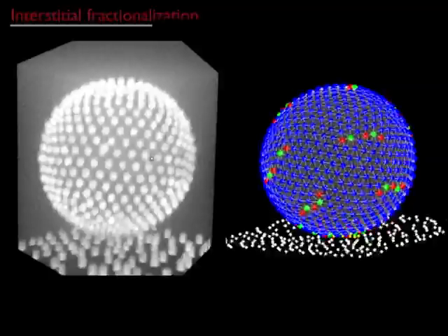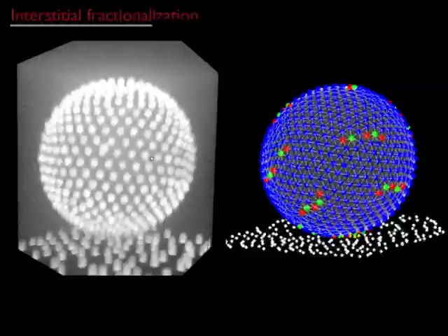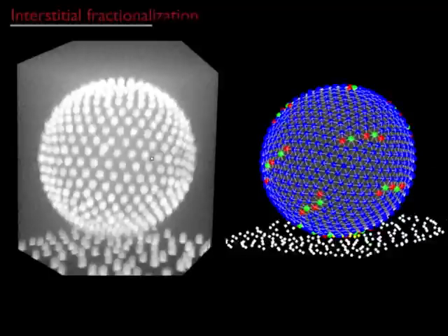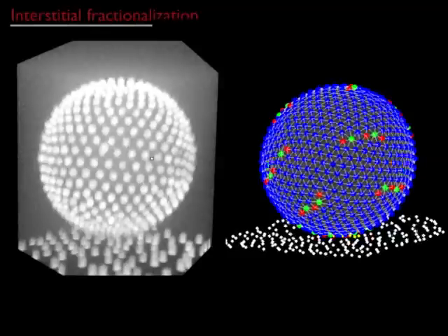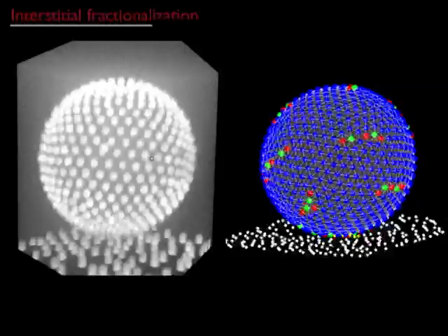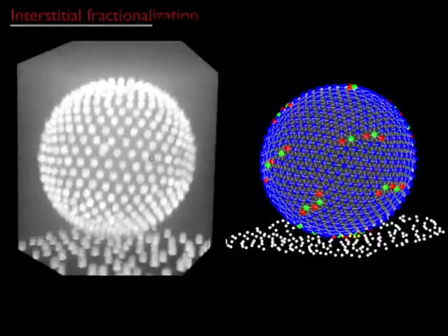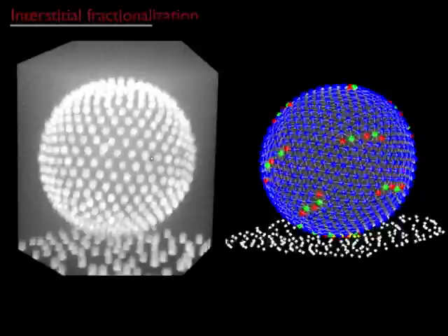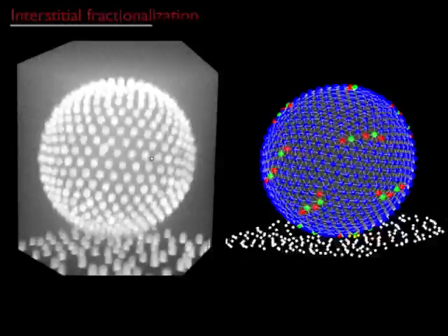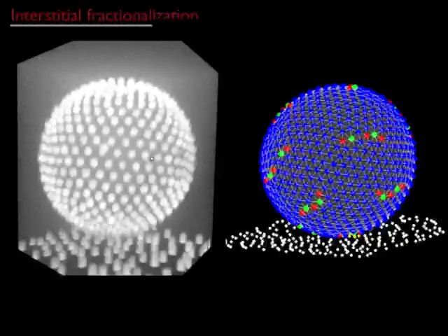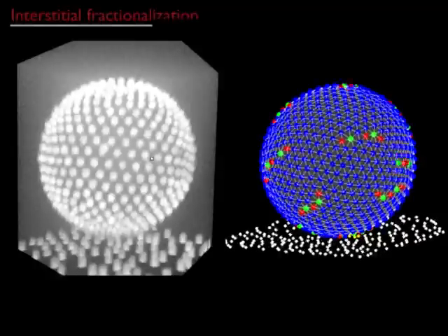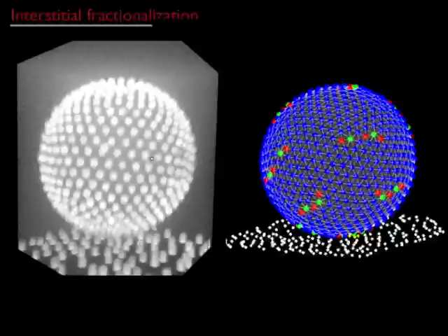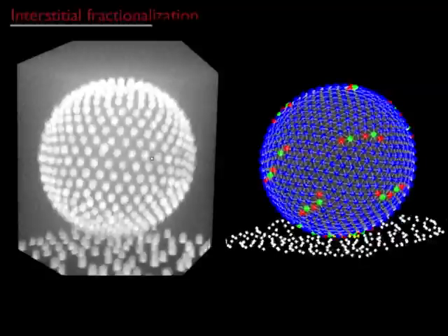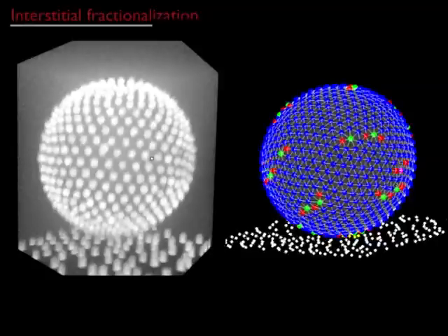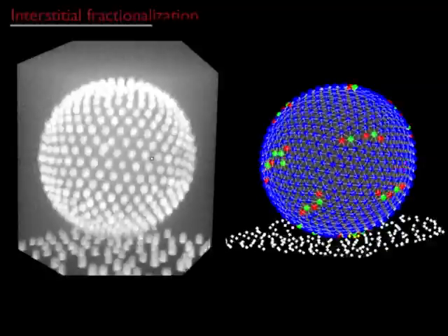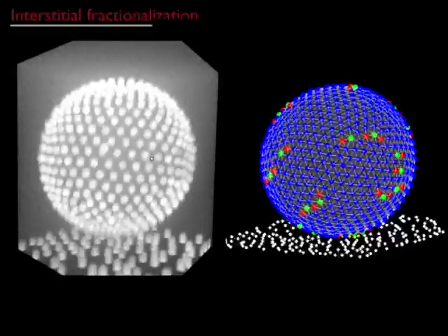Where's the particle? What happened to the particle that I added? Well, of course, the particle's there. It's one of these guys. But if I look at what happened to the extra density that I added to the system, half of the density went that way, and half of the density went that way. And it's perfectly right. This is the same thing that happens in solitons. It's the same thing that happens in domain walls, in crystals. And it's completely a classical effect.